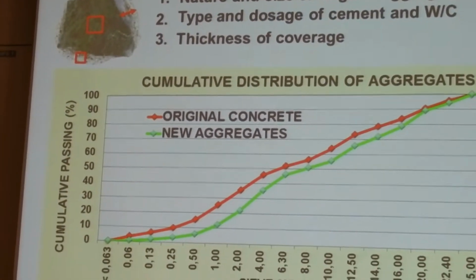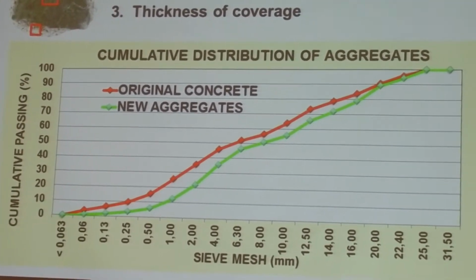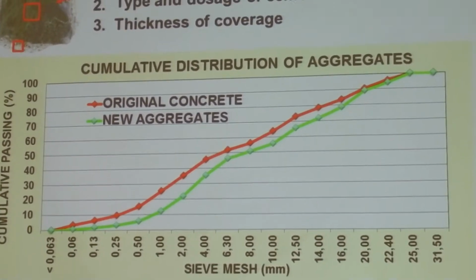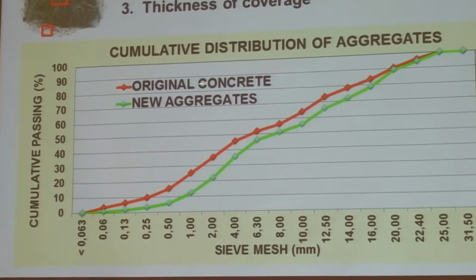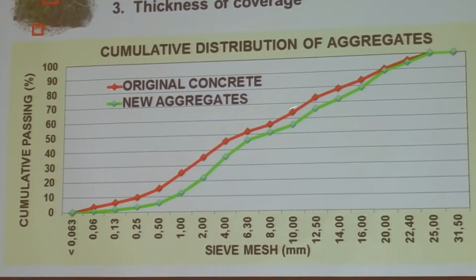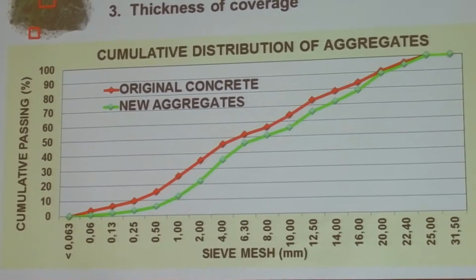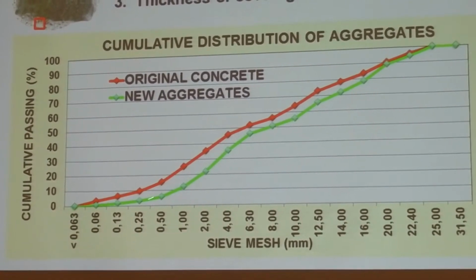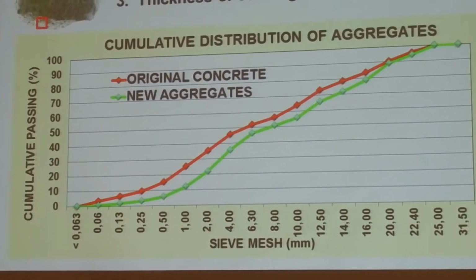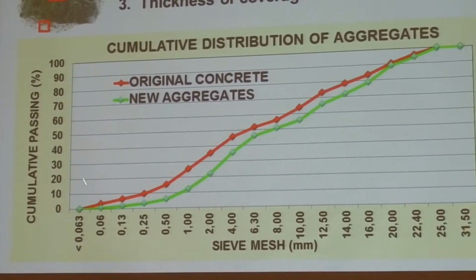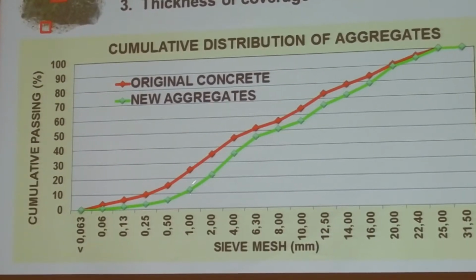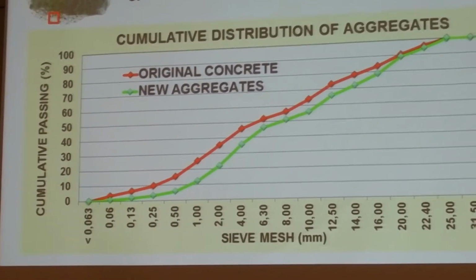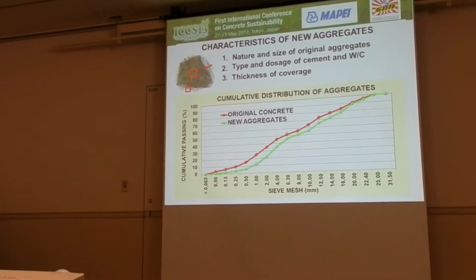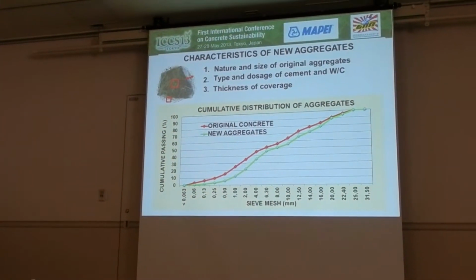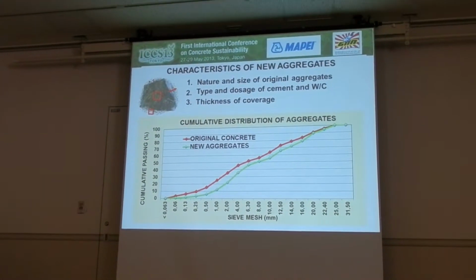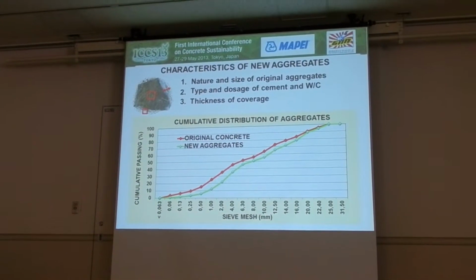The typical distribution of the new aggregate is represented in this graph. You see, this is the distribution curve of the original aggregate in the returned concrete. And this is the typical distribution of the aggregate you obtain from returned concrete after the treatment. You see that you have a lower fraction of fine material, because the fine material coagulates onto the coarse aggregate, and so you have a lower amount of the fine fraction.